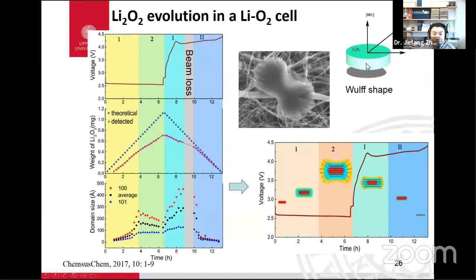So this is the structure for lithium oxide. We measured 100 and 101, these two directions, the pattern peaks. Then, according to the relationship between these, we could also deduce the information for the 001 direction. As you can see, by the domain size change, we can divide the formation and the decomposition of lithium oxide into 2 stages, both in discharge for the formation and in charge for the decomposition.